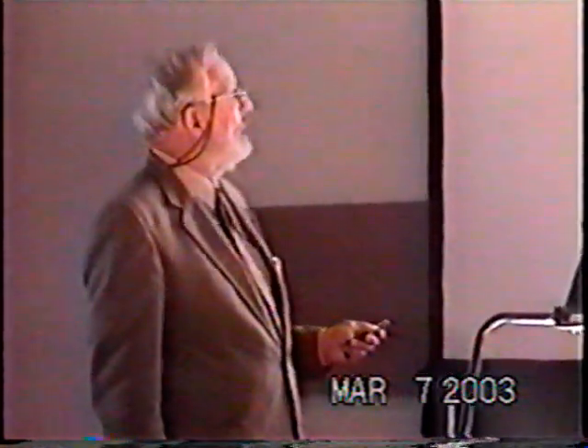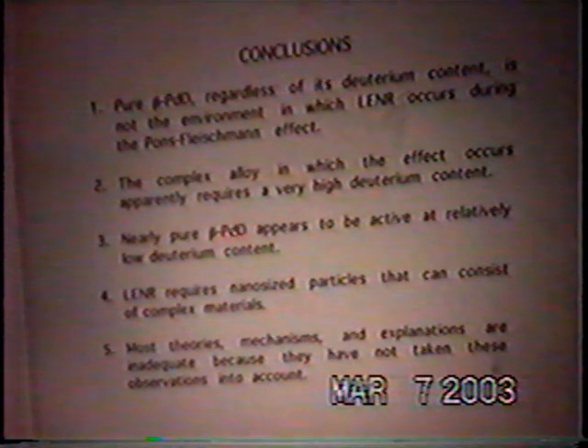So the conclusions that I would like to suggest to you: pure palladium deuteride, regardless of its deuterium content, is not the environment in which an LENR occurs during the Pons-Fleischmann effect. The complex alloy in which the effect occurs apparently requires a very high deuterium content. On the other hand, nearly pure beta palladium deuteride appears to be active at relatively low deuterium contents, and this is using a different technique. LENR requires nanosized particles that consist of complex materials. And lastly, most theories, mechanisms, and explanations are inadequate because they have not taken these observations into account.